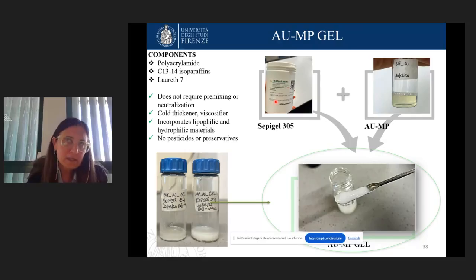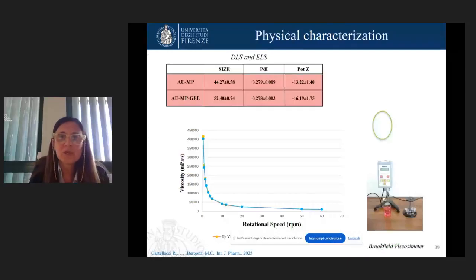This is a synthetic gelling agent that produces, at 1 or 2%, a very good stable gel. The constituents of the Sepigel are a polyacrylamide, an isoparaffin, and laureth-7. Sepigel contains a lipophilic phase, but also a tenside inside the formulation. We prepare different gels with 1 or 2% of Sepigel in water, and we add the micelles.